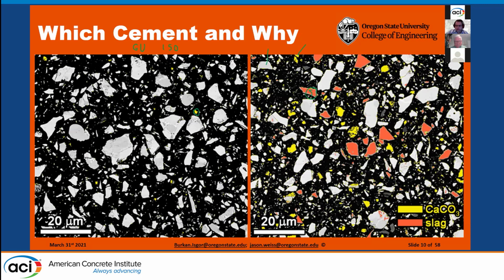In our conventional OPC system, we have a little bit of limestone addition, usually around 2 to 3, 4%, somewhere in there. As we move to the right side, all of a sudden the yellow particles go up, and we get to about a 10 to 12% portion of the system, which is pretty typical. You'll also notice that the yellow particles tend to be smaller, and as Doug mentioned, this is because they grind a little bit easier in the overall system. But this one also has some slag that's been mixed into the system.